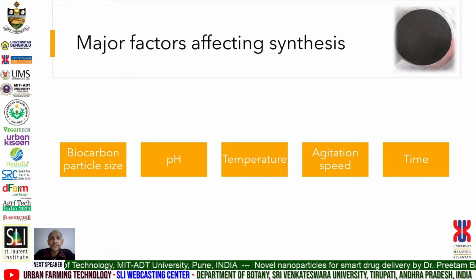Increasing temperature can also affect particle size distribution and polydispersity. Particle size decreased with increasing stirring or agitation rate. Particles disperse into smaller droplets. Higher agitation reduced growth kinetics, resulting in smaller sized particles. Sonication is suggested especially when dealing with large reaction volume. The larger particles can also be obtained by aggregation of the small crystallites.